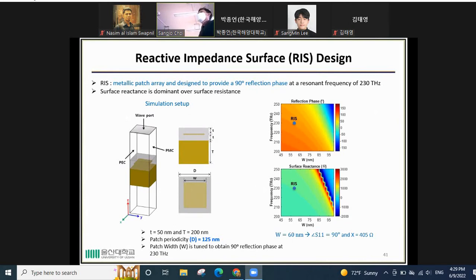We also use a reactive impedance surface (RIS) to optimize the nanopiece for perfect absorption and maintain high field enhancement. This RIS is a metallic patch array designed to provide a 90-degree reflection phase at the resonant frequency of 230 terahertz. This surface also has higher surface reactance at the resonant frequency, and this is the schematic view of the RIS. We use 50 nanometer thickness for the silicon dioxide and 200 nanometer thickness for the reflector. We use a patch periodicity of 125 nanometers, and then the patch width is tuned to obtain a 90-degree reflection phase at 230 terahertz. From this tuning, we obtain that a 60 nanometer patch width provides a 90-degree reflection phase with surface reactance of 400 ohm.